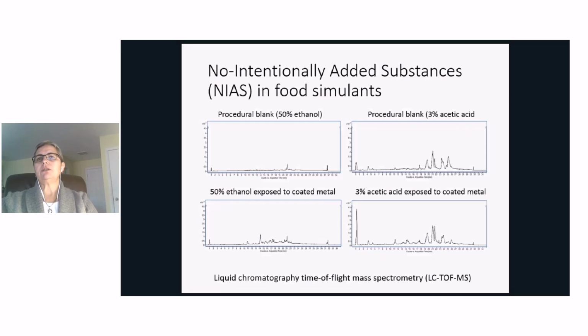Very quickly here, these are images of the non-intentionally added substances in the food simulants. The chromatograms on the top are for the blanks for both simulants, ethanol and acetic acid, and the bottom are the chromatograms for the extracts. In both cases, there were 650 masses detected in the ethanol extract and 651 in the 3% acetic acid extract. There was not an attempt to identify those masses.